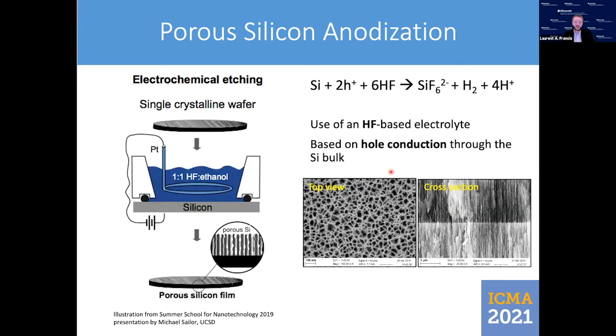A quick word about the fabrication of porous silicon itself. By electrochemically etching a monocrystalline silicon, we have the so-called porous silicon anodization. The principle is very simple. We place a silicon wafer, preferably p-doped, in an etching cell containing an electrolyte based on hydrogen fluoride. Then we pass a current through the cell which induces the chemical reaction, creating the pore as described here. As you can see, the reaction is based on the hole conduction through the silicon bulk. Pore size, thickness, and porosity depend on 3 factors: the HF content, the current density, and the etching time.